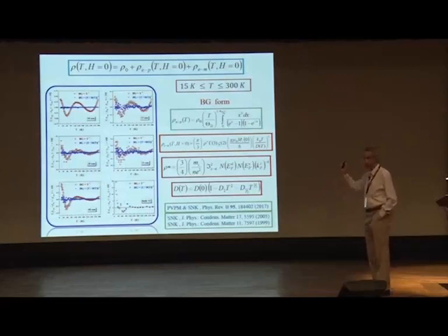Okay? Now, once we bring in the renormalization of spin wave stiffness into it, you see that not only are the deviations reduced by an order of magnitude, but they are now statistically distributed around 0. That means you now have the right functional form, which describes your observed data properly, and we can actually estimate accurately their different contributions.